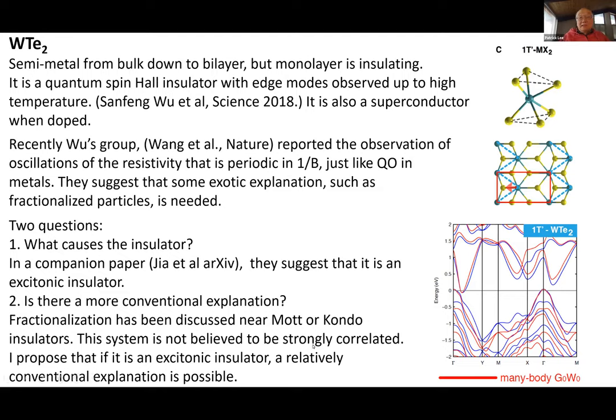Now the focus of this workshop is on the quantum oscillation. The question is what's the explanation? Sanfeng Wu's paper suggested fractionalization and so on, but I find that not so well motivated because fractionalization is usually seen in strongly correlated materials near Mott insulators or Kondo insulators. My instinct is to try to find the simplest explanation as possible. I propose that if it were an excitonic insulator, then a relatively conventional explanation is possible.